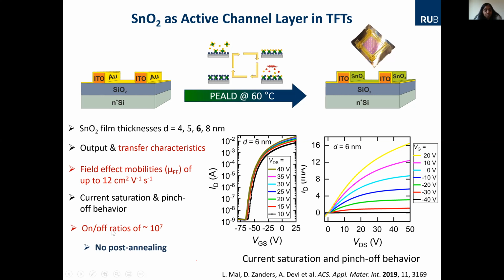And of course, the on-off ratio is very important, because for switching applications this will be very good, and we have around 10 to the power 7. We have to keep in mind, all these are as-deposited films. There was no annealing done after the deposition. That means the as-deposited films are actually stoichiometric and also functional. So this summarizes the electrical properties.